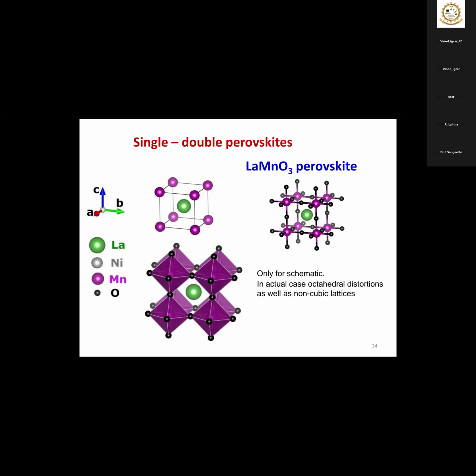Lanthanum will be at the center. Manganese will be at the corners. No oxygen in the top left figure. Now I have added oxygen, that is the top right figure. You can see each manganese will be surrounded by 6 oxygen atoms along the a, b, c crystallographic directions, or you can assume X, Y, Z Cartesian coordinates: plus X, minus X, plus Y, minus Y, plus Z, minus Z. Like that, 6 oxygen will be there. Now I have drawn the bottom left figure with the octahedra. You remember in the first talk we discussed octahedra. This is one example, LaMnO3. Like that LaMnO3 repeats in all 3 directions to give the crystal structure.